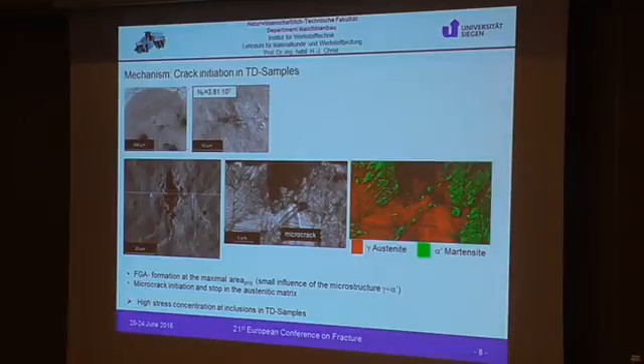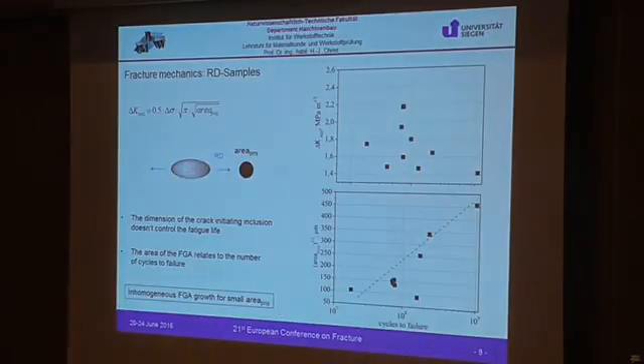All these statements, however, have a more or less pronounced assumption character, so we also applied fracture mechanics theory in order to support these statements. For the RD samples, we calculated the stress intensity at the inclusion, and we see only a very weak correlation between delta K and number of cycles to failure. This is explained by a very strong influence of the local microstructure, especially for very low delta K values beneath 1.8.